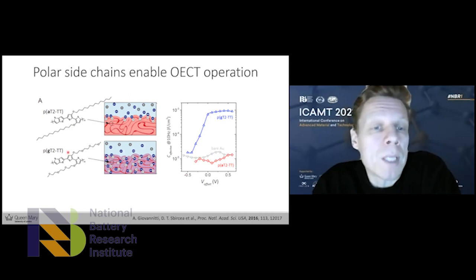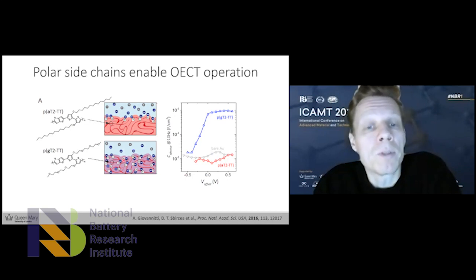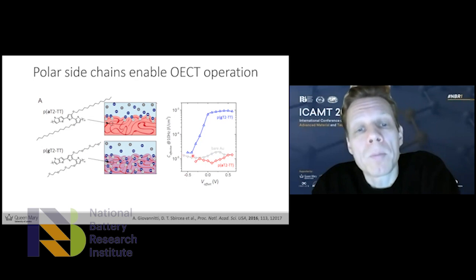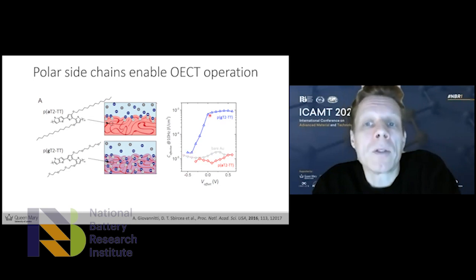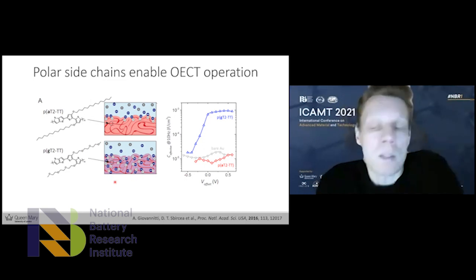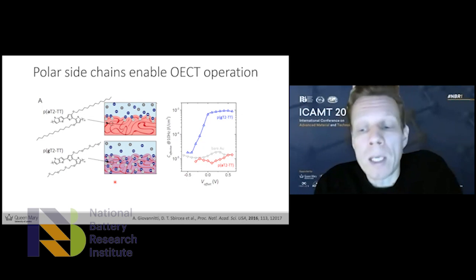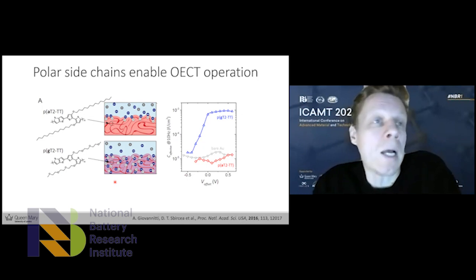On the other hand, if we decorate the polymer with these very polar side chains, now we see that the ions enter into the bulk of the film, and we can dope the entire polymer film, which is, of course, important for generating lots of charge carriers. And we see that in the effective capacitance, once we apply a small bias to sort of force the ions to go into the film, we see a 2 to 3 order of magnitude increase in the effective capacitance, telling us that this cartoon here is a nice representation of what's going on. We get bulk doping of the film due to these ions entering into the film and compensating the electronic charges that we build up with the bias.